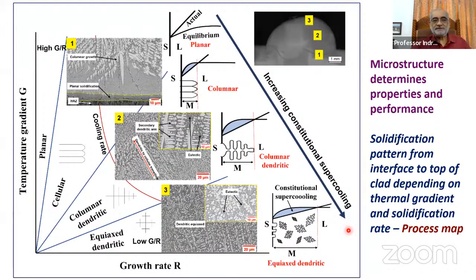I wish I had more time to discuss it. So essentially, we know in case of solidification processing, there are 2 important aspects we are talking about, the thermal gradient and the growth rate. And with this, I can actually create a process map. And from that, I can predict under what regime I'll have very high G by R ratio and hence a planar growth front. And on the other hand, what would be the lowest range of G by R ratio so that I can get equiaxed structures. So in the process, this is how I can control the microstructural gradation with increasing or decreasing amount of constitutional supercooling or the phase separation or solute segregation during the processing itself.